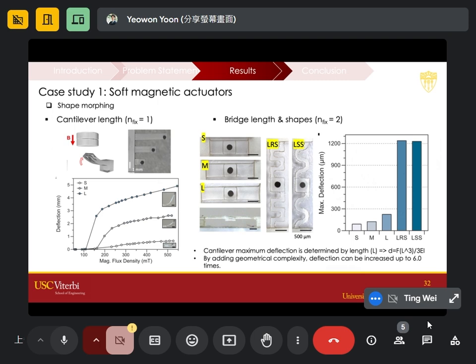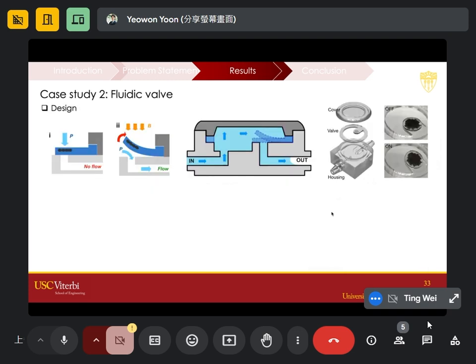This one is to show off with 3D printing what we can do with the magnetic particle insertion. The first idea we had is, what if we use it as some sort of magnetic valve? The idea is we have a normally closed valve, like a flapper, and then we apply pressure. Normally the pressure pushes the cantilever beam down, so there's no flow out and the valve is closed. But whenever you have a magnetic flux coming in, the cantilever reacts and goes up, and through this opening the pressure goes through and you have a flow. So the first one is off, and the second is on with the flow.